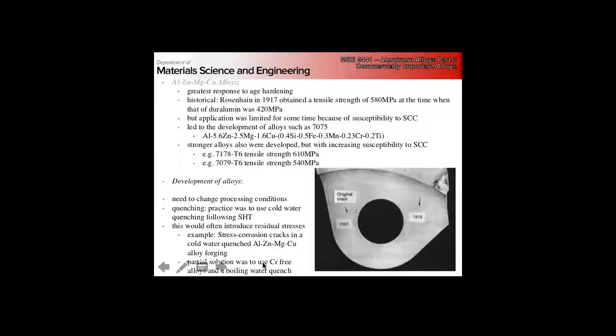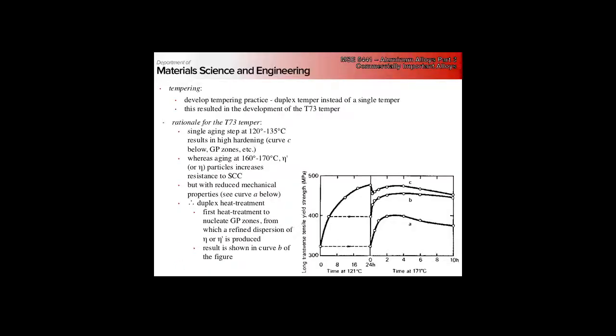And so part of the solution was to basically use a boiling water quench rather than a cold water quench. But the biggest change was the development of a duplex heat treatment, which resulted in something that's called the T73 temper. And the rationale for this is pretty straightforward. Single aging step, at 120 to 135, which is sort of where we saw the optimal was for a lot of different alloys.